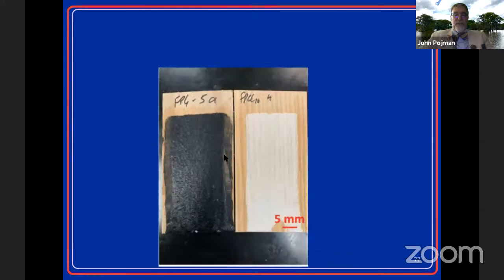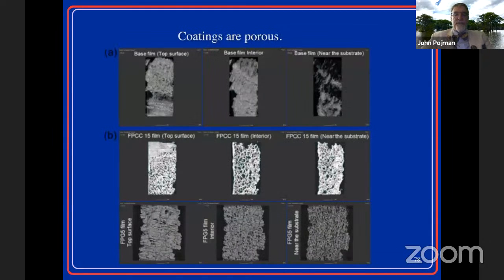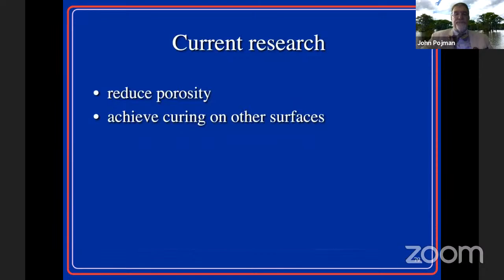And here are examples of what the cured layer looks like. This is on pine wood. One problem is the coatings are rather porous. Doing micro CT, micro tomography on it, we can see that it's about 30% porous. That's caused by byproducts of the polymerization reaction, the initiator decomposition. So one area we'd like to work on is trying to reduce that if you want to have a more solid material.